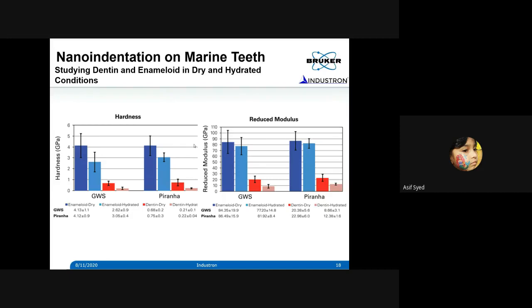Now let's look at the average properties of those two types of specimens. One is the white shark, another is the piranha. On the left side is the hardness, on the right side is the reduced modulus. If you compare, you can see that on the enamel part, in both hydrated and dry condition, there is a small difference, but not as much as you expect. You can see both piranha as well as the shark have similar hardness. That's why their bite is pretty strong, we know that, right? And if you look at the dentin properties, they are also pretty much comparable between piranha and white shark. And the same thing with the reduced modulus.